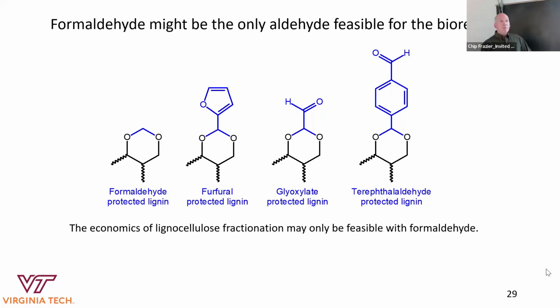There must be free formaldehyde, and so that formaldehyde has to be stripped. Yes, but the good news is that it can be stripped. So it's not even in methylol form. It's actually free formaldehyde. So yes, in this process to produce this lignin, there's such an excess of formaldehyde that has to be stripped out. The formaldehyde that's incorporated chemically is incorporated in carbon-carbon bonds. And so it's hydrolytically stable. And so it's not going to be an issue with formaldehyde emissions.